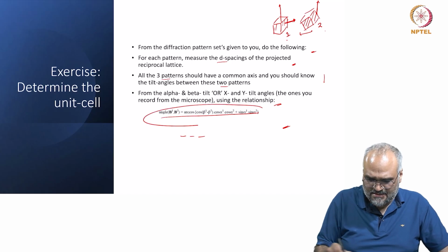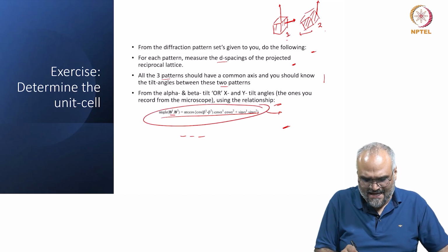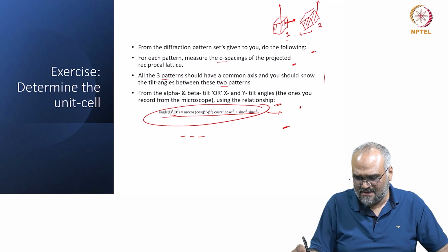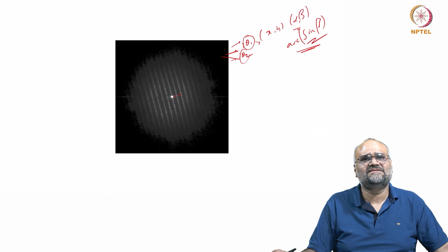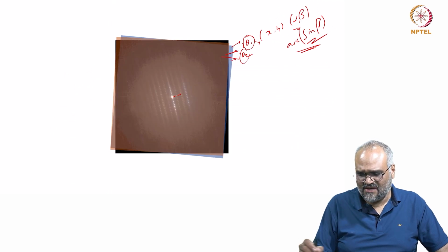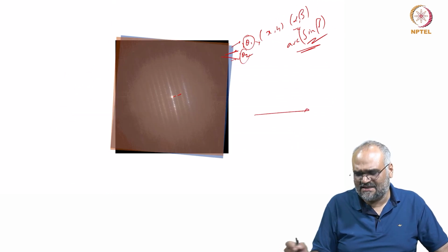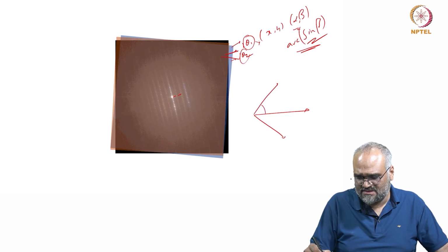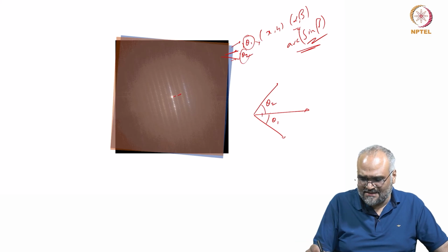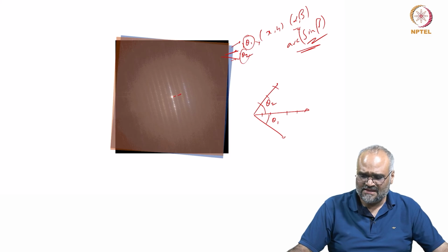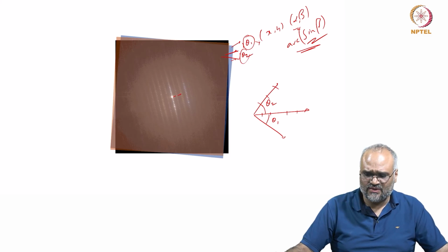From this particular relation, the angle between the diffraction patterns would either be a positive value or a negative value, and from 3 reflections like this, if I determine one of the intermediate values as the horizontal line by measuring the D1 and D2 values and representing these as theta 1 and theta 2 and marking the distances on a graph paper, I can actually start seeing a projection of a unit cell. So, that is what I will show you in the next slide.